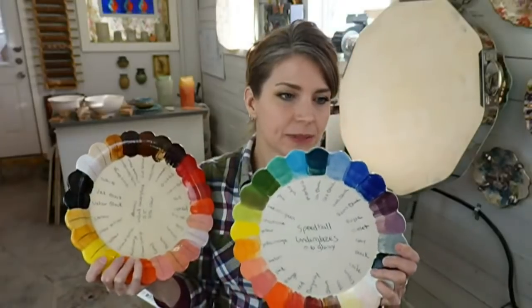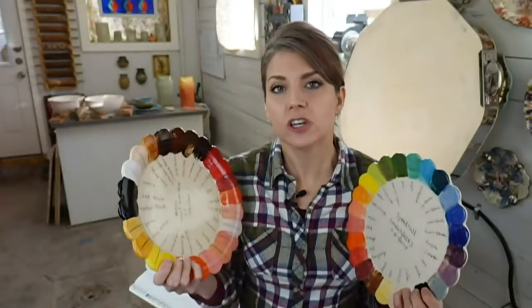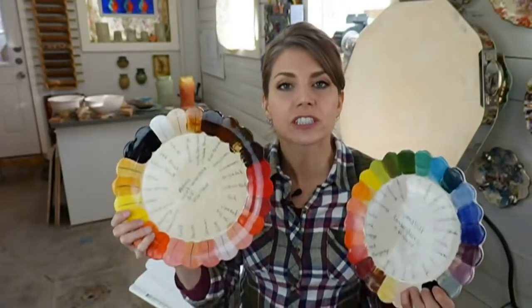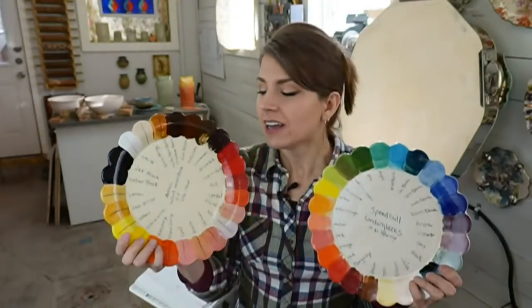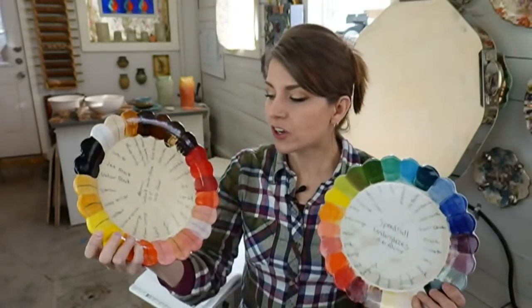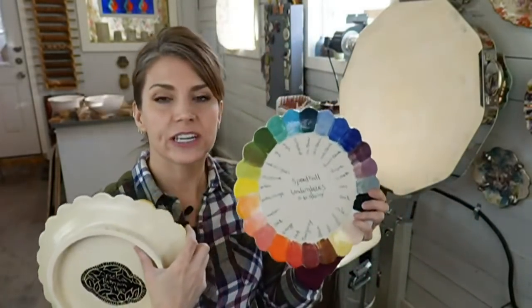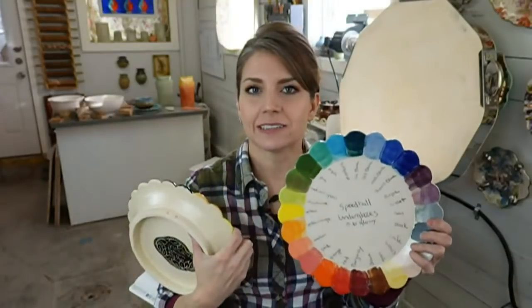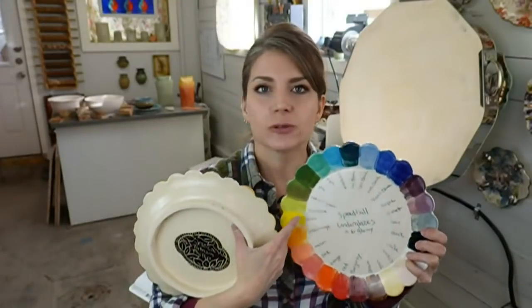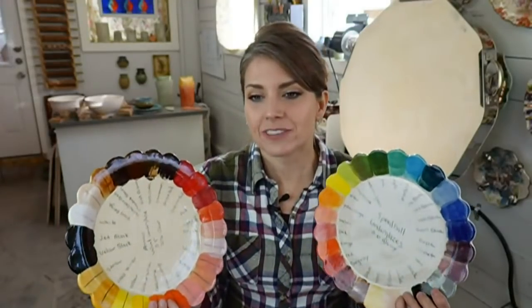Difficult to mix underglazes because they're not exactly the same color wet as they are fired. Right, so what you need to do is know what you get. Just over time, using your underglazes, you'll become familiar with them and you'll know what they look like. The other thing you can do is if you know you're going to mix your yellow and say your chartreuse together, or your yellow and your pine green, write down 50% yellow, 50% pine green, mix it up in a little container, put it on here and do a test. Just write down what you're mixing and do tests. That way you have a reference for that, so you know what it's going to look like, right?